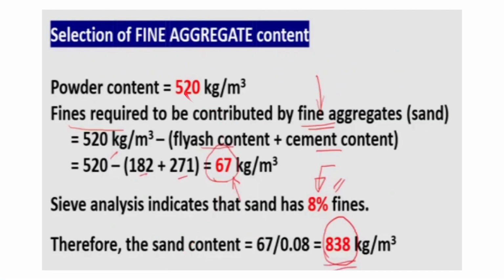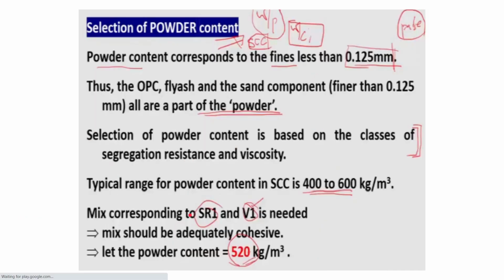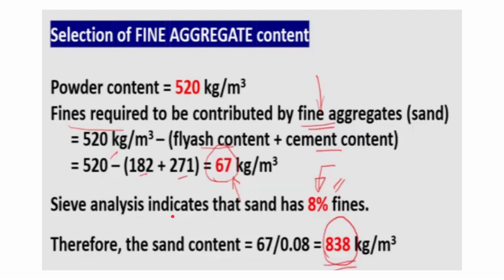So we have to subtract 182 and 271 from 520, and we get 67 kg per meter cube of fines, that is sand, which is having size less than 0.125 millimeter. This sieve analysis, it has been found to be a standard value, gives 0.125 mm passing fines as 8%.